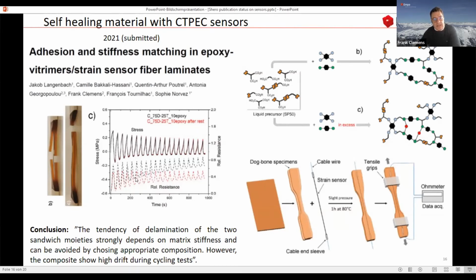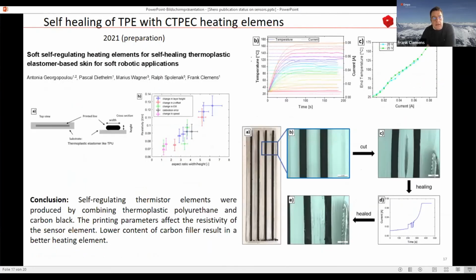Nevertheless, you can see that there must still be some improvement, because we have a high drift of the sensor behavior according to the cycle number. To show that even self-healing properties are possible by using a simple TPE material, a thermoplastic elastomer without any hydrogen bonds, we started to develop these self-regulating heating elements, which we integrated in our matrix material.